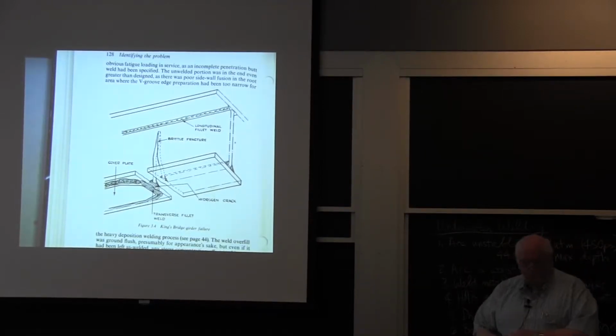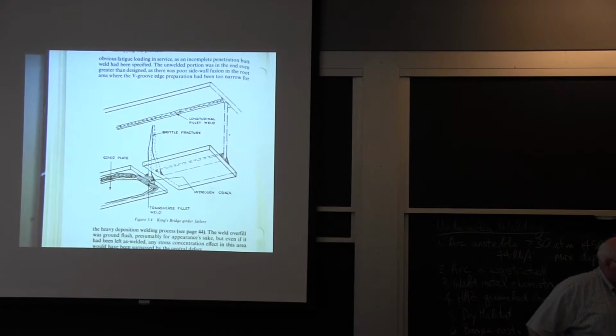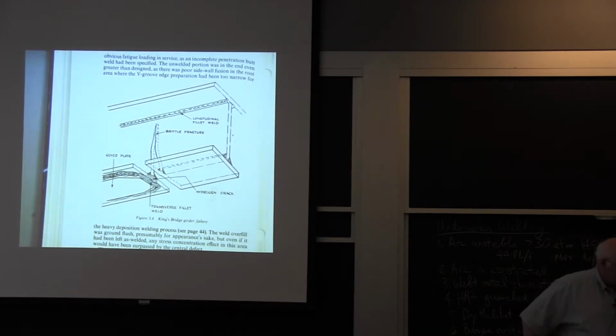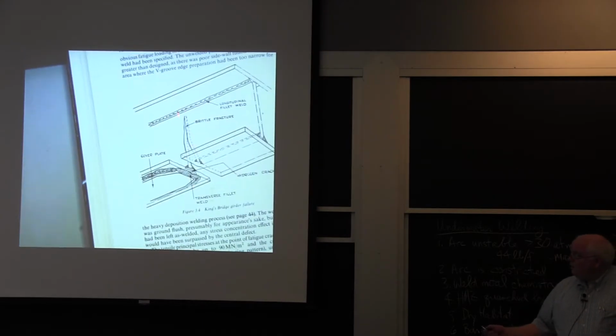So this is the King's Bridge I mentioned yesterday, I guess, and here is the weld detail on one of the girders that was holding up the bridge, and they developed a fatigue crack at the toe of this weld. Lots of restraint as you go around. Developed a fatigue crack, and then they had a brittle fracture go up through there. Okay. Like I said, no one got hurt or killed. In fact, as you look at the picture, the thing didn't even break all the way through. The top flange didn't break through the top flange.